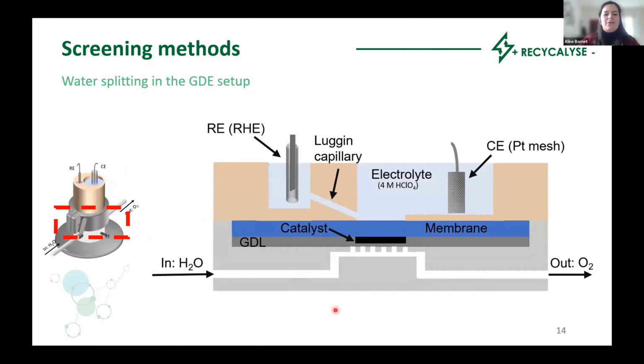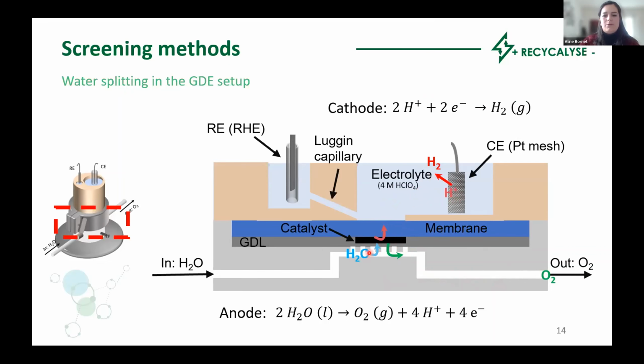We see that it's a 3-electrode system with the catalyst being our working electrode. We have a counter electrode, which is a platinum mesh, and the reference electrode. The electrolyte is 4 molar perchloric acid, which is separated from the catalyst by a membrane. So we don't have a direct contact. And all of this works like this. Once the reactant, the water, reaches the catalyst, it oxidizes to oxygen, which leaves the cell, and to protons, which pass through the membrane and reach the cathode, where they are being reduced.